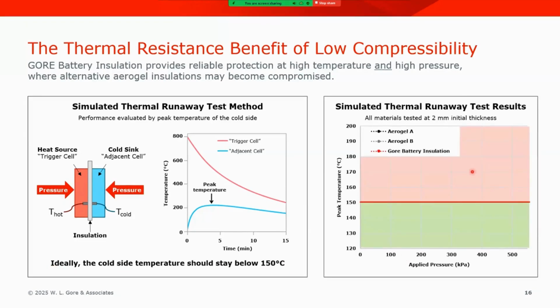Now we're going to plot our data over here on the right. And in this plot, we have on the x-axis the applied pressure. Remember, this is discrete points in multiple experiments. And then we're going to compare that to the peak temperature over here on the left side. And ideally, at all of these pressures, the peak temperature should remain below 150 C. All of the materials that I'm going to show were tested at an initial 2 millimeter thickness.